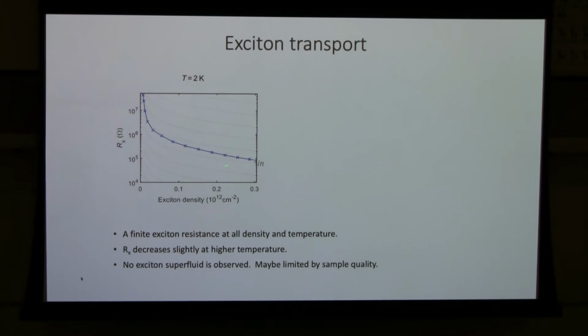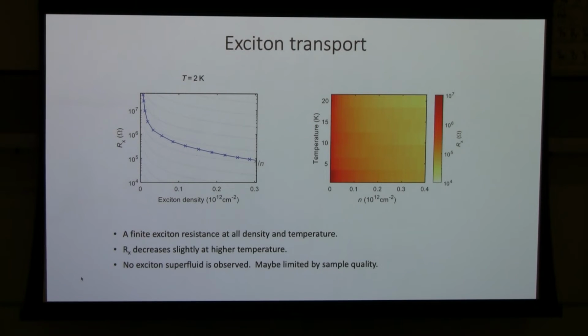Here we show the exciton resistance we measure as a function of exciton density. You can see the effective exciton resistance is still pretty large. It goes from megohm to the high tens of kilo ohm. And it decreases with exciton density roughly following a 1 over density behavior, which is the classical behavior that one would expect. We can also measure it at different temperatures. So this is the resistance as a function of density and temperature. What we see is it doesn't have a very strong temperature dependence. If you look carefully at high density, the exciton resistance actually decreases a little bit.